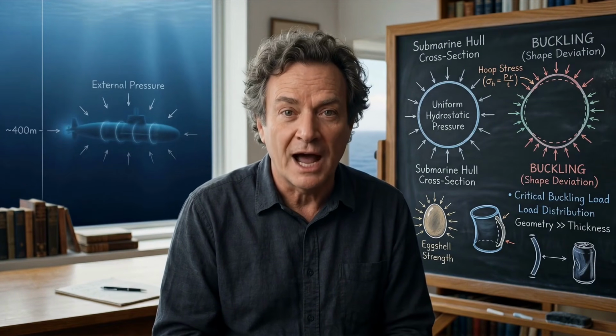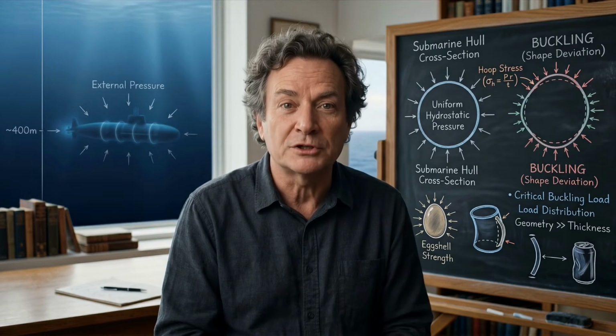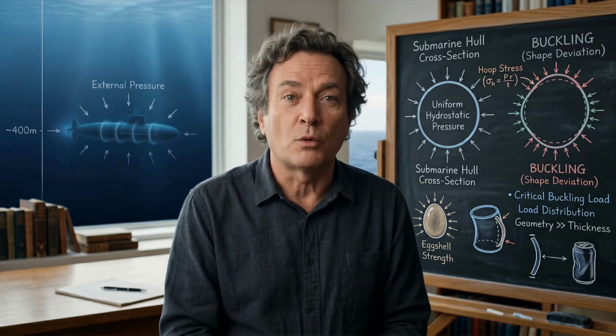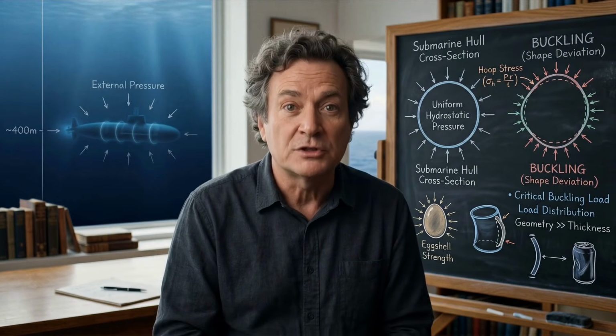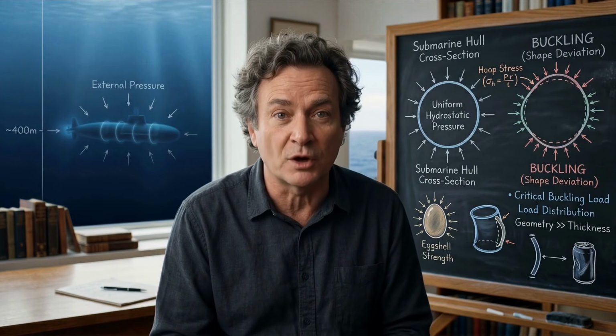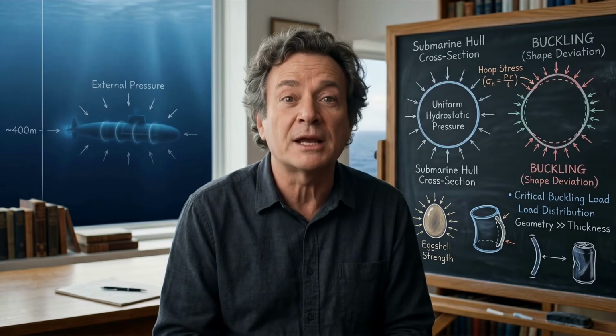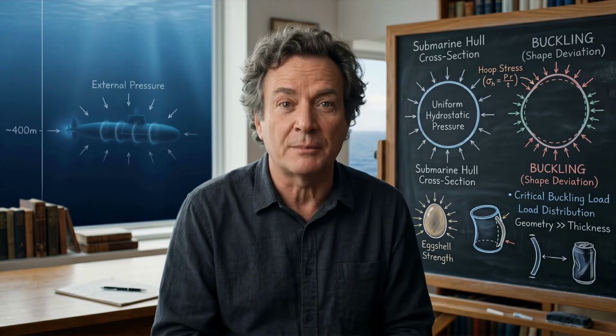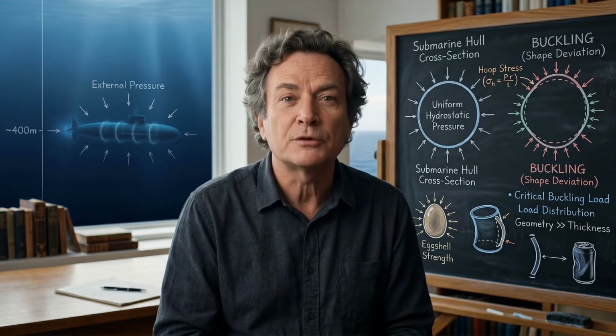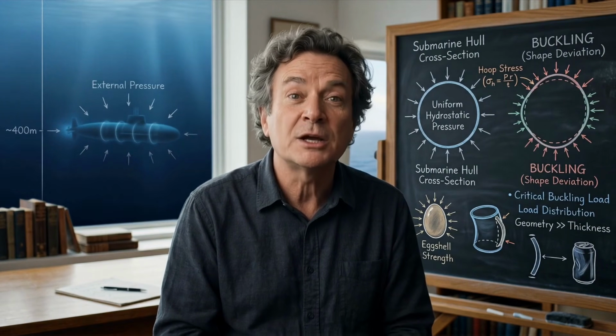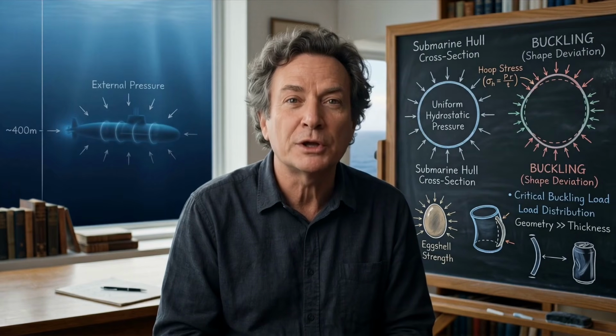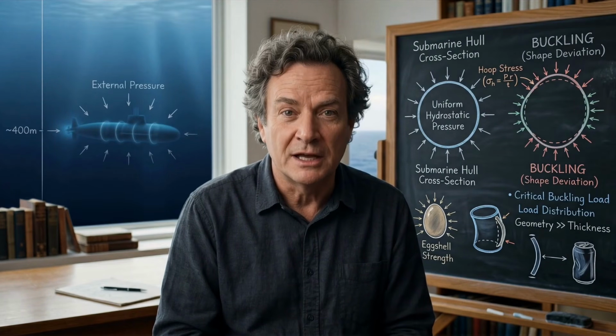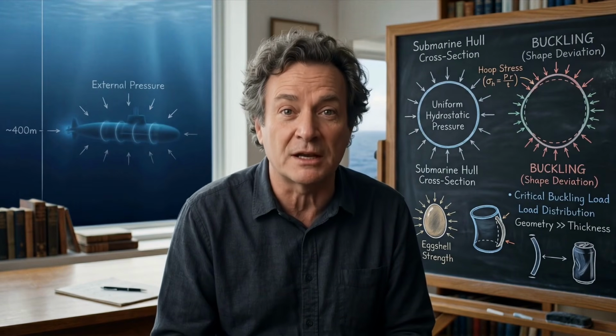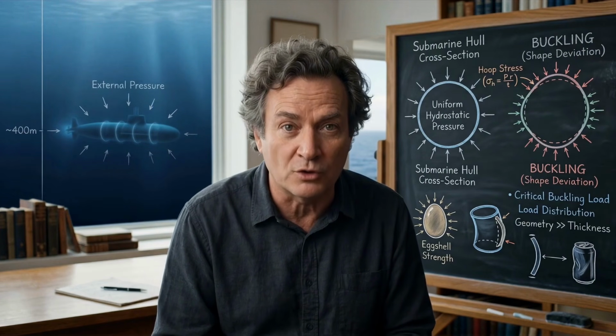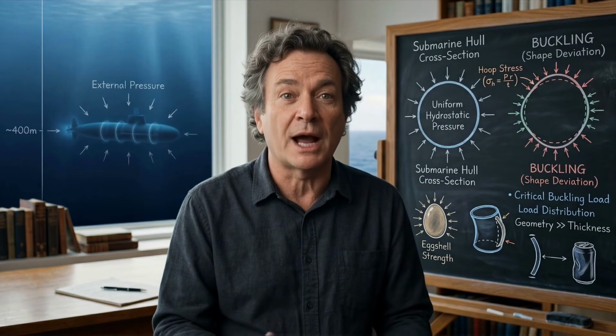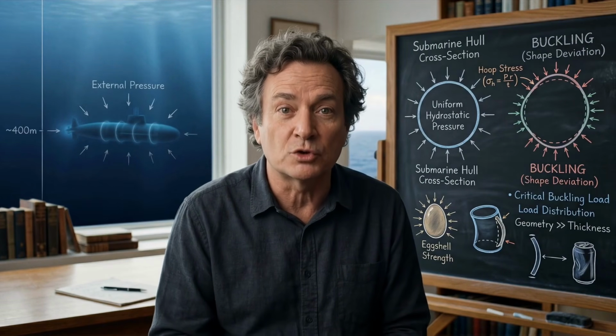The HY stands for high yield, which means the material can be stressed to very high levels before it permanently deforms. HY80 yields at about 80,000 pounds per square inch, roughly 550 megapascals. That is a phenomenal stress capacity. But the interesting thing from a physics perspective is not the yield strength alone. It is the relationship between yield strength and toughness. Toughness is the ability of a material to absorb energy before fracturing, to deform, to accommodate stress concentrations, to not crack catastrophically. And here's the uncomfortable truth.